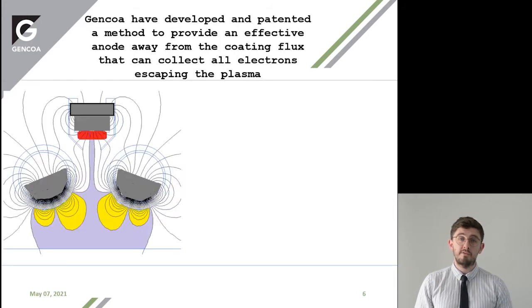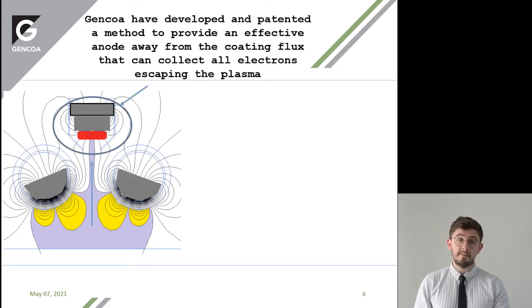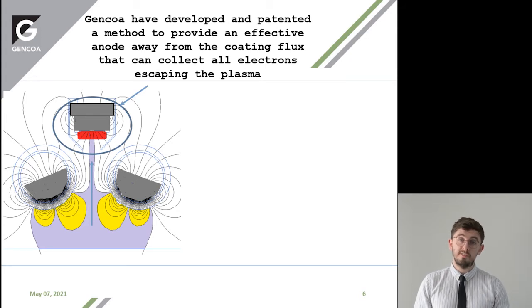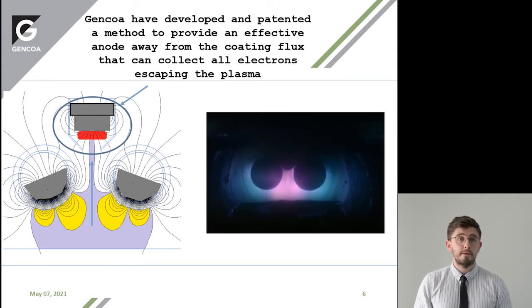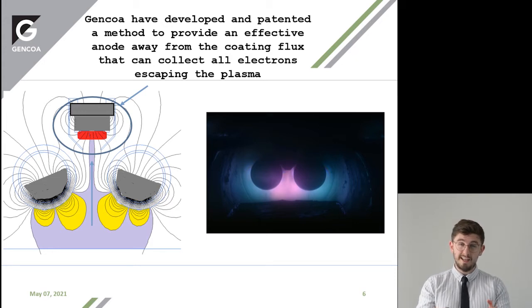Gencoa developed a method to alleviate this issue for AC systems, and also offer some improvement for DC pulsed systems as well. You can see the anode is now defined here. Due to the magnetic attraction of the anode, we can confine the electrons to the region where we want them, in between the targets.